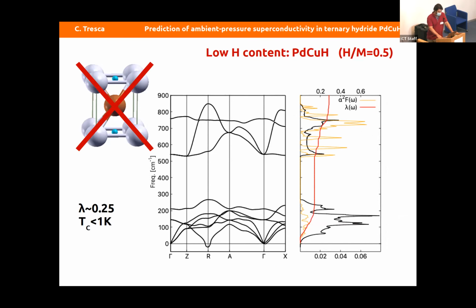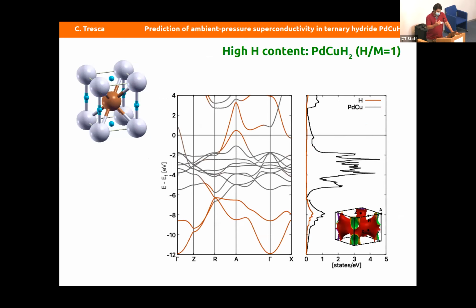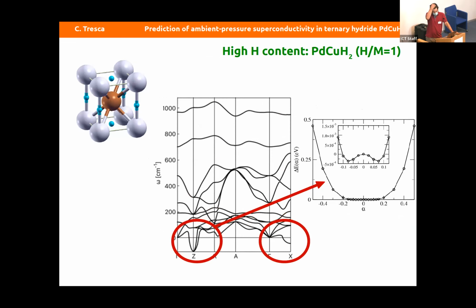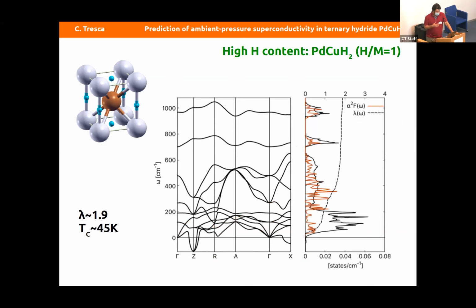We move to the high hydrogen content in palladium copper hydrides. The doping of the hydrogen is still present. And from the dynamical point of view, we see that at the harmonic level, we have some dynamical instability that we studied in the adiabatic way following the relative eigenvector. And from the study of the energy profile, we can conclude that those positions are the equilibrium positions for hydrogen, dynamically stabilized. We noticed that now the gap is absent, and this produces a higher electron phonon coupling that now is 1.9 with a critical temperature of 45 K.